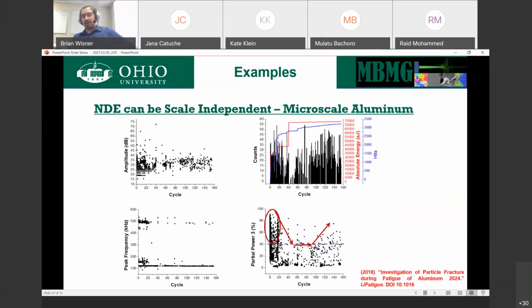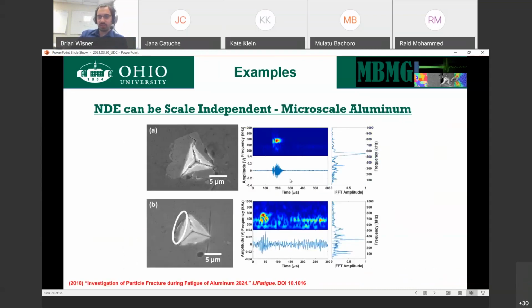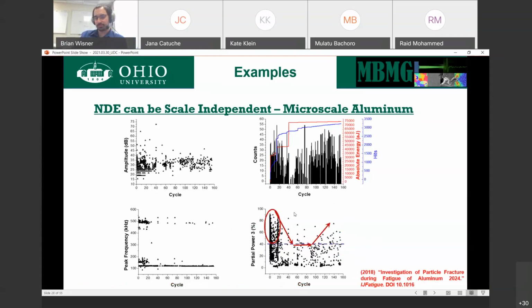We can then extend that and use just that to talk about other properties. In this case, fatigue, low cycle fatigue in this case. Looking at this waveform, we can take it, we can characterize it. We can say it has high amplitude. We can say it has high frequency, between 500 and 600 kilohertz. We can figure all of these things out and plot them.